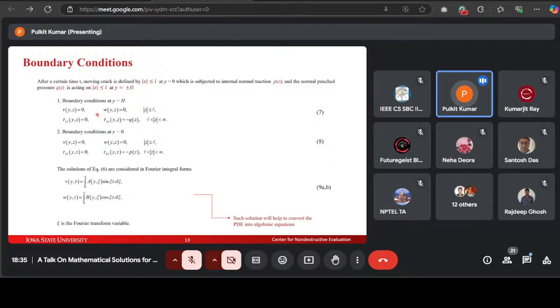Because of the punch pressure, we consider the surface becomes rigid. As the surface becomes rigid, the displacement in this part will be 0, because there will be no deformation. That is why the displacements V and W are considered to be 0 where we consider the punch pressure, and the stress is 0. The next condition is that the normal traction or the normal punch pressure is equal to minus Q of z, and the boundary condition at y equals 0 is similar.